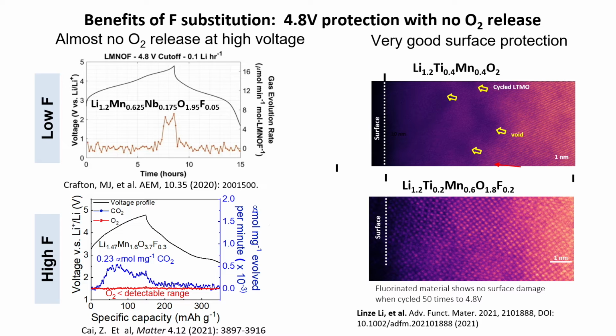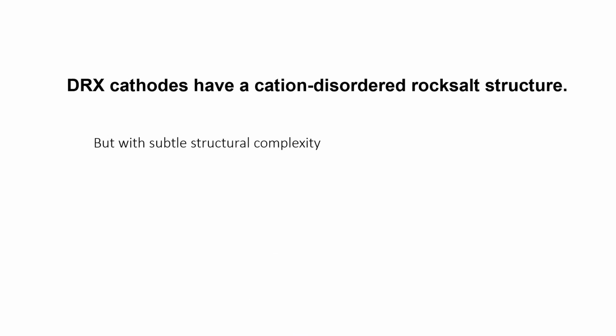This is some data from Changmin Wang at Pacific Northwest National Lab. If you take a disordered rock salt without fluorine and compare it to a similar one with fluorine, these are cycled 50 times to very high potential. It's a little hard to see, but this has undergone all kinds of corrosion holes, essentially where materials have dissolved, and the fluorine-containing material is perfectly intact. Essentially, it's because, as Raphael said yesterday, fluorine is an extremely electronegative ion. It's almost impossible to oxidize it unless you go to really high potential.